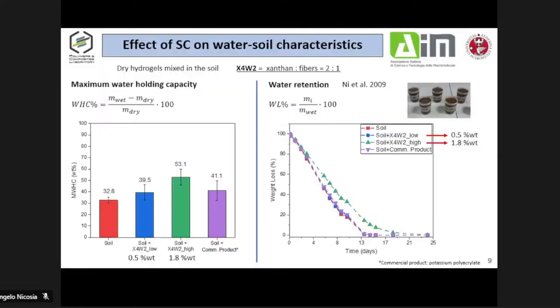So what about the soil conditioner? We studied the effect of this material on soil. In particular, I report the results only for the sample characterized by this xanthan to fibers ratio. About the maximum water holding capacity, which is the maximum water that the soil can absorb before reaching saturation, we found good results just by adding small quantities in weight of our material. We also found better results with respect to a commercial soil conditioner, a superabsorbent polymer based on potassium polyacrylate.